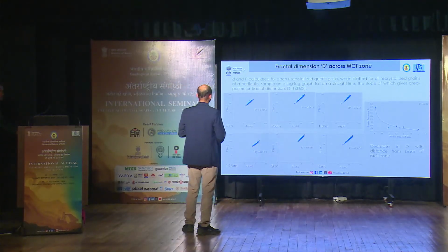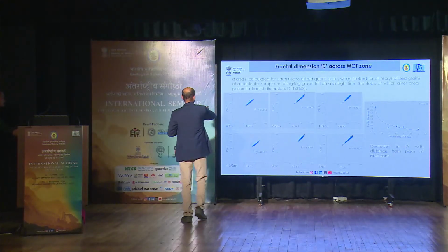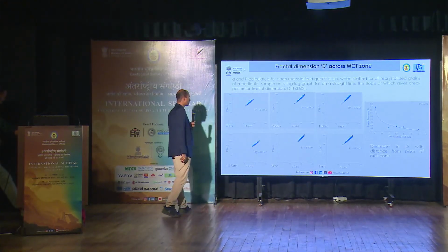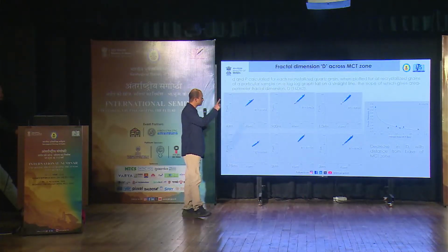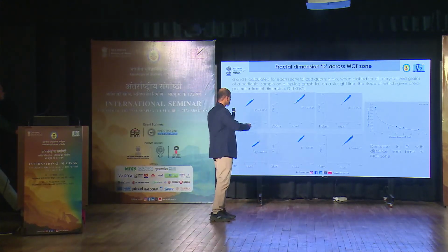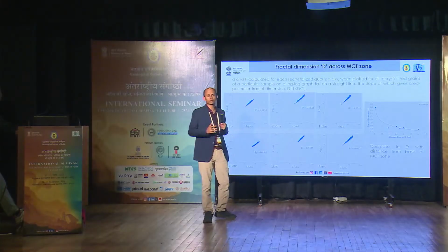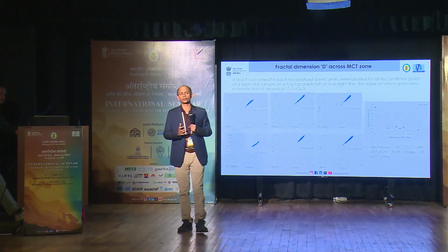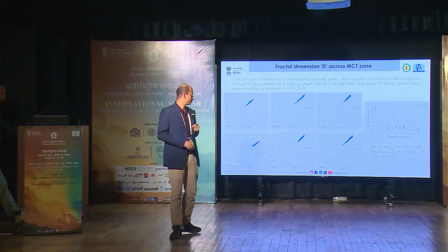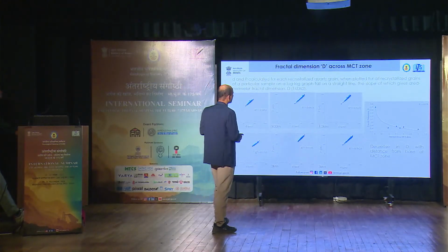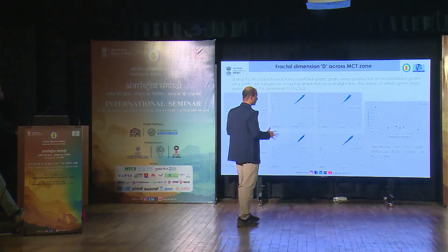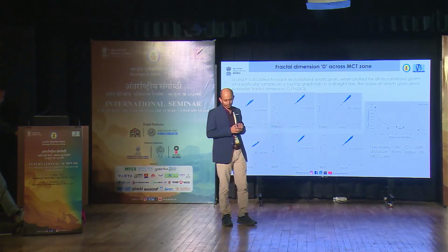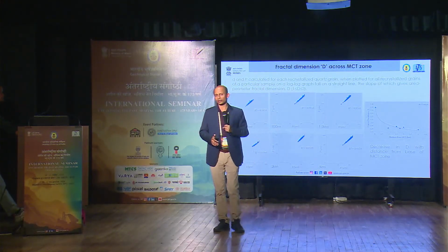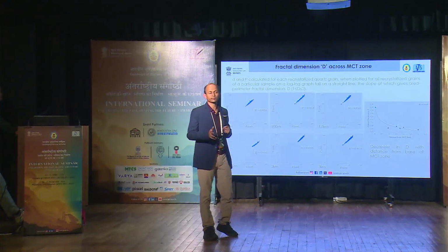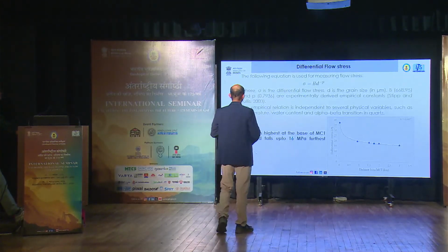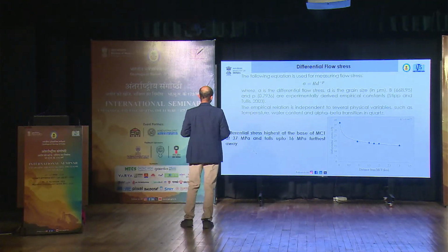So basically, the y-axis is the perimeter, the x-axis is the quartz grain size. We see all are falling in a straight line, with high R squared, which means it is showing self-similarity, or fractal behavior. So what we have observed is that right at the base, the area perimeter fractal dimension is highest, and as we go away, the area perimeter fractal dimension falls, which is evident from the increase in grain size.